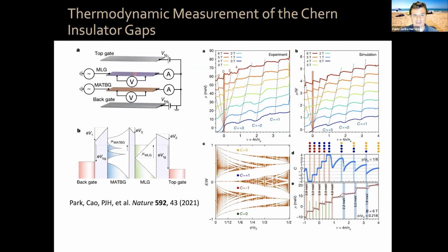More recently also, we have applied a new technique, okay, using chemical potential, but not by using scanning SET, as I mentioned with the group of Shahal Ilani, but now we can have our magic angle twisted bilayer graphene next to monolayer graphene. And by tracking the charge neutrality point of monolayer graphene in a dual gated structure, okay, this is the band alignment of the system, you can actually measure the chemical potential of the magic angle twisted bilayer graphene. Okay? Now, when you measure that chemical potential, here's a measurement, for example, of the chemical potential as a function of filling factor, and at varying magnetic field, you can see steps in your chemical potential. Those steps correspond to the Chern insulator gaps, okay? So we're measuring the Chern insulator gaps, okay, as a function of magnetic field. And here you have the values of those gaps. So these are the first thermodynamic measurements of the Chern insulator gaps, which you cannot measure in a transport experiment. You can do a thermal activation, but it usually doesn't give you as much information.